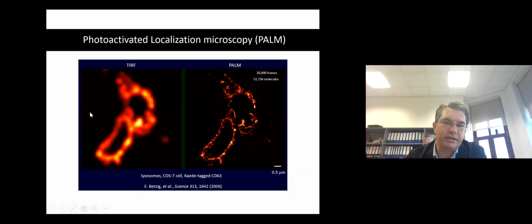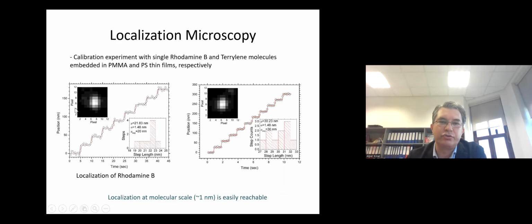Well, for the other two techniques, we don't have a contribution, just to give you the information. So in the PALM technique, photoactivated localization microscopy, what you do is you activate your fluorophores in the sample one by one. Okay, only a few of them are activated at once. Then they are photobleached, then a new cycle begins. So following each activation, you localize each of these molecules. Localization means you record these single molecule images and you find the center of mass of these images.